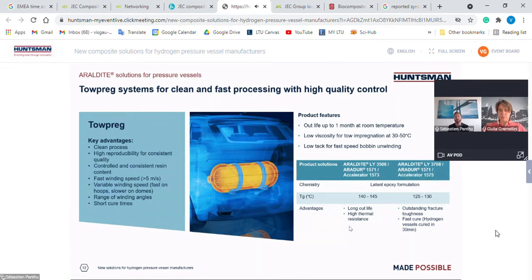So all of those players have understood the advantages of this type of product. It's also a clean process. It provides very high reproducibility, a very constant and consistent resin content, a very fast winding speed, up to 5 meters per second. And as well, we could demonstrate that we can shorten the cure times a little bit versus wet filament winding. We have two examples of systems here, which are latent epoxy formulations. The first one has, for example, a shelf life of up to 1 month at room temperature, and this can be further increased if you reduce the temperature to between 2 and 8 degrees, for example, then you go to several months.